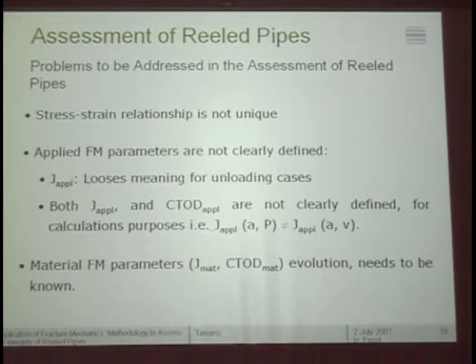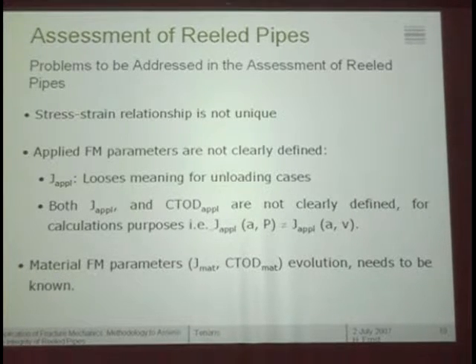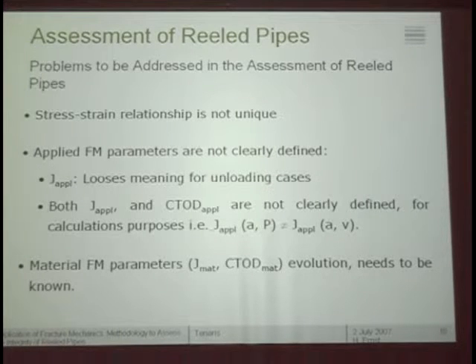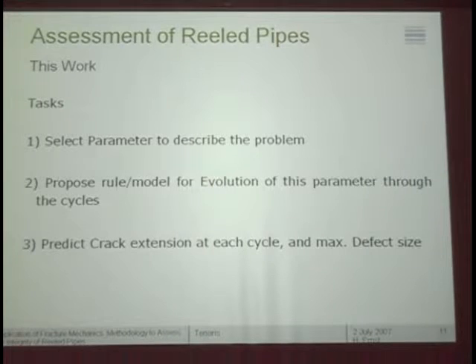That is, if you have a J as a function of crack length and load, or J as a function of crack length and displacement, they both must agree. And in this case, since the load displacement or stress strain characteristics is not clearly defined, because it's not unique, then you cannot use the regular equations to do that. Of course, we also, as I said before, need to see how the material resistance curve, we call it material fracture mechanics, J or CTOD versus delta A, evolves. That needs to be known, as I said, again, instead of the sentence that I mentioned before.